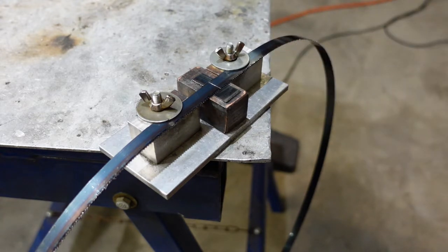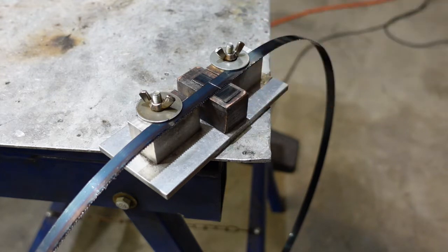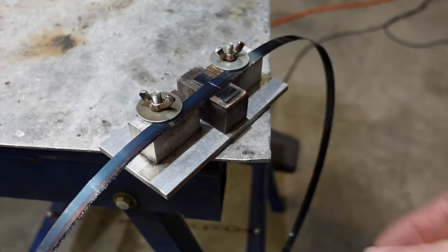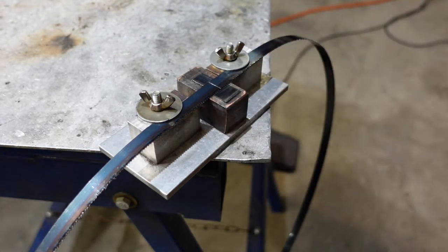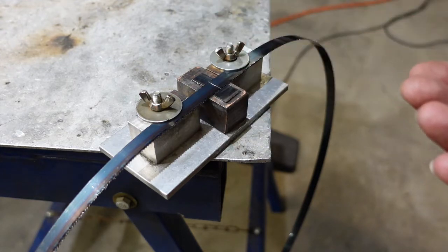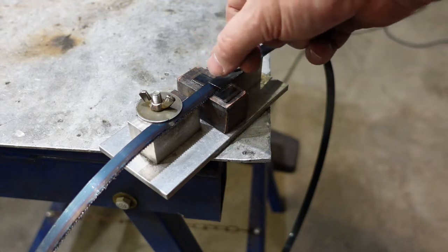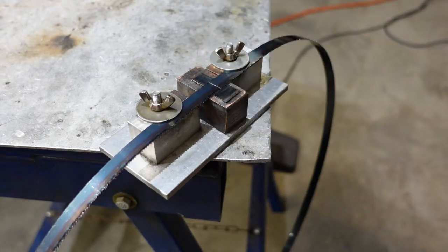Now this blade material is I think 0.65 of a millimeter thick, it's half inch wide, and usually I have the welder set on around about 40 to 45 amps. You don't want much otherwise you'll just blow straight through it. The copper backing helps keep the bead on the reverse side flat, also helps control some of the heat, but that lets me go along and weld.